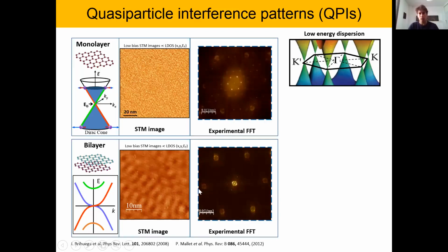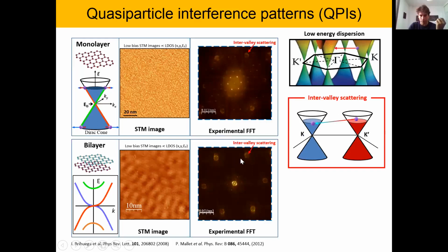And then we get a complete map of many frequencies where we have the different scattering events of quasiparticles with the defects that we have. So for example, if I concentrate in this high frequency region, these ring-like features that you see here, those scattering processes correspond to electrons which change the valley. They go from valley K prime, for example, to valley K, as you see here. This is known as inter-valley scattering processes. The electron goes from one valley to the other valley.